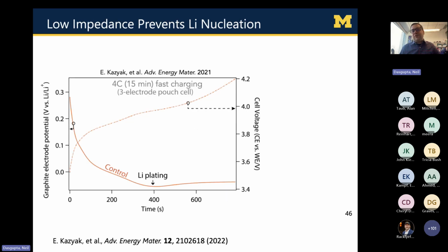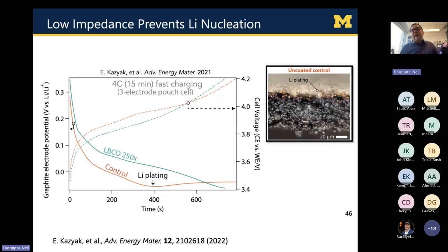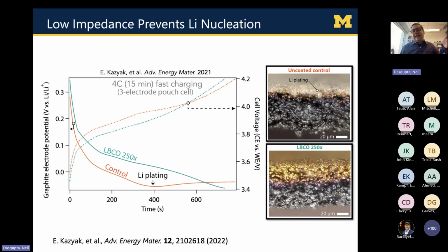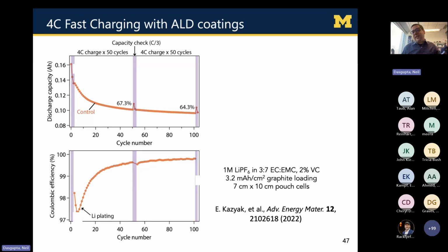So now we go to our 3 electrode cells and we see the control cell, we see the signature plating that I already showed. We're again able to eliminate that by doing this ALD coating on the graphite electrode, and that enables us to fast charge the battery without lithium plating, which was really a surprising find because most people would argue you have to solve the mass transport limit to enable fast charging. But here we showed just changing the interface enables fast charge.